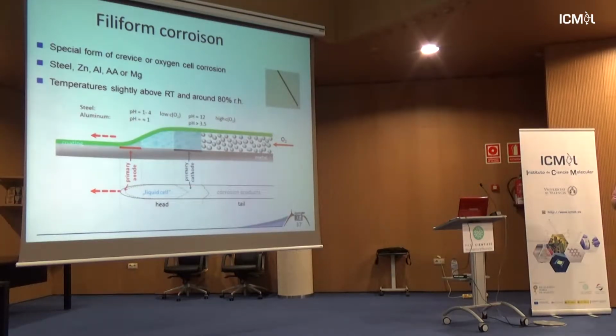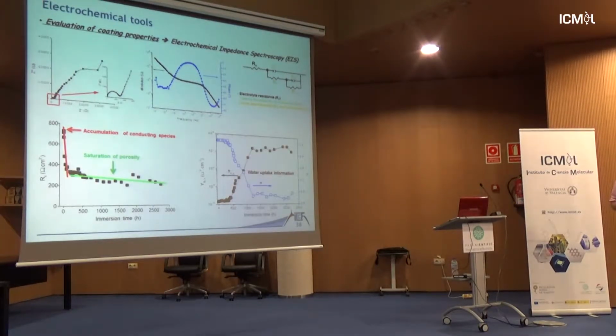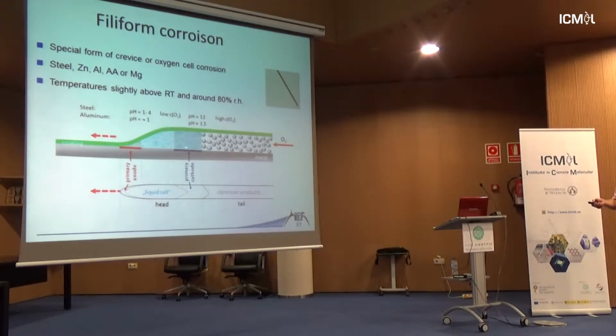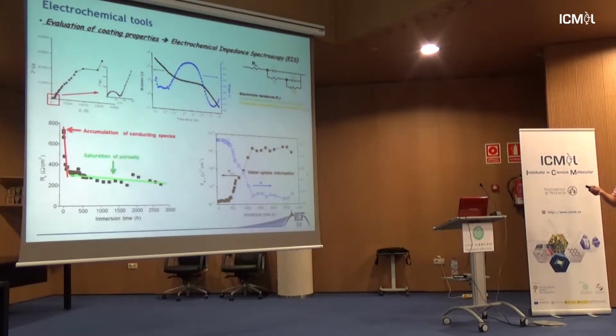That's a polymer coating. So in both scenarios, you may have some occurrence of the LDH to protect or to fight against the corrosion, because of dissolution here and because of the anion exchange here. So we tested, I will not go into too much detail, different electrochemical characterization using impedance spectroscopy that can model what is occurring beneath the coating, because you have one electrode on the substrate directly, and the other inside the medium, the salty water solution that you put on the face of your coating, and you can model in fact all the interfaces involved. So that's the interface here, that's the interface here. All the interfaces you can model by a circuit here, and so you can end up with the corrosion resistance of your coating. I will not go into too much detail unless you have questions here.